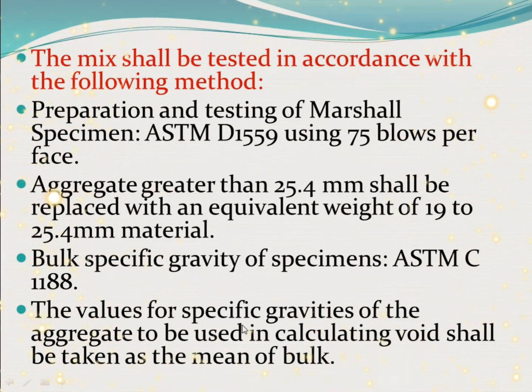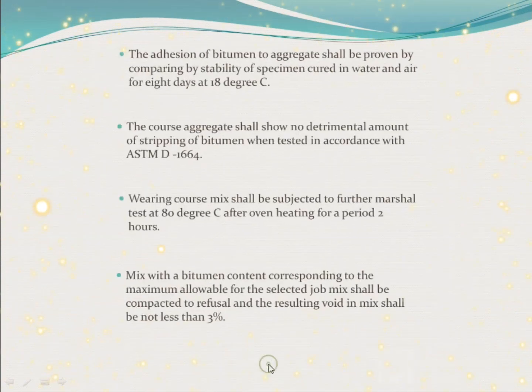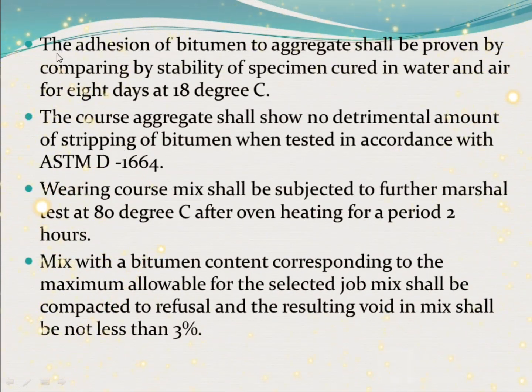The values for specific gravities of the aggregate to be used in calculating void shall be taken as the mean of bulk. The adhesion of bitumen to aggregate shall be proven by comparing the stability of specimen cured in water and air for 8 days at 18 degrees centigrade.